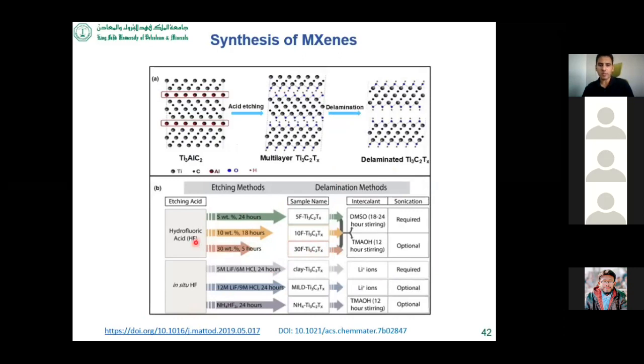How can we optimize the synthesis conditions? Traditionally, HF, or hydrofluoric acid, was used for etching of the MAX phase. But of course, anyone in this area must know that it is a very dangerous and very toxic acid, so it is very hard to work in this area. But if you increase the concentration of the acid, of course, the reaction time will be reduced. With 30%, you will get your etching in just 5 hours. But again, if you use a smaller concentration, you wait longer to get the MXene.